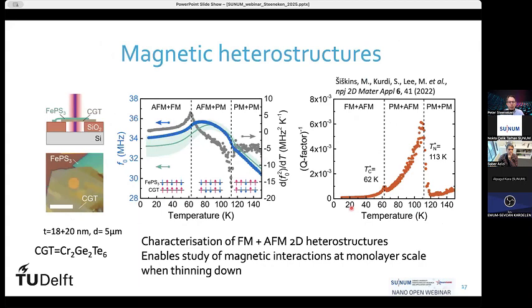A final topic that we tried is to make stacks of 2D materials. We put two different 2D materials on top of each other, and then when we cool this structure down and look at the resonance frequency, we can detect the phase transition in the first material, that's the iron phosphorus trisulfide, and in the second material, which is the CGT, the chromium germanium telluride.